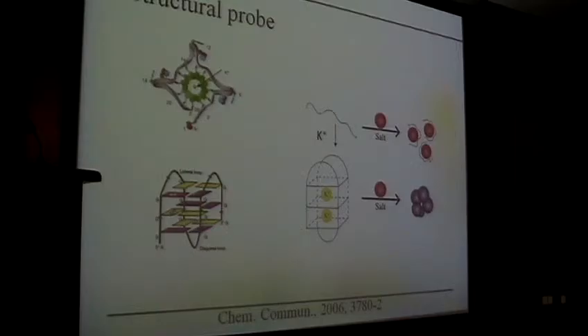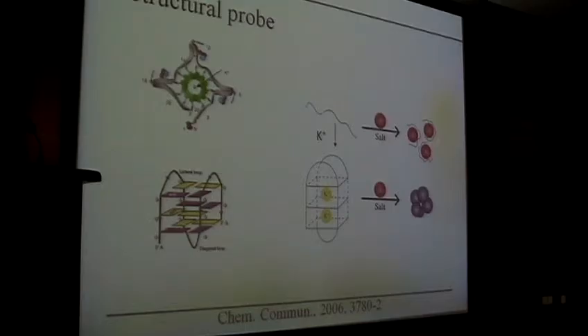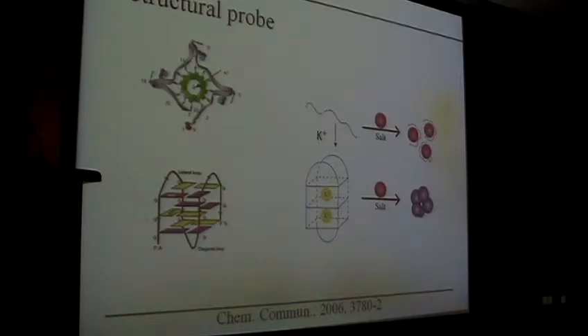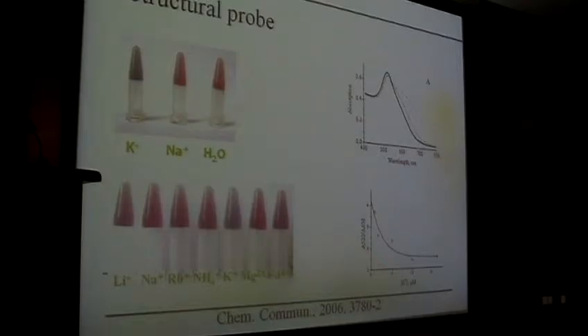This is an example. We show that this DNA strand, which contains many guanine residues, can bind to potassium very specifically and form a G-quadruplex structure. So we expect that if there is no potassium, it will protect gold nanoparticles from aggregation. But if there are potassium ions, it forms this structure and can no longer protect the gold nanoparticles. Indeed, in water with no potassium it's red, but with potassium ions it turns blue, while with sodium it cannot bind and remains red.